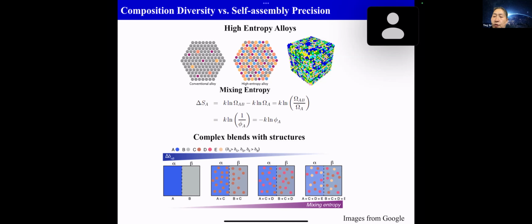And by the time you add in four or five or six components, you begin to have multiple formulations that will give you the same effective interaction between the alpha and the beta phase. And at some point, the interaction between the alpha and beta phase can be completely equal to zero. So that means the system is miscible, but yet the system will give you the structure. And looking at the alpha and the beta phase, you also begin to have formulation flexibility. So what you see is that as you increase the system complexity and diversify the chemical building blocks, as long as you follow certain rules, there are possibilities to really get into this high entropy alloy type of version in soft matter.